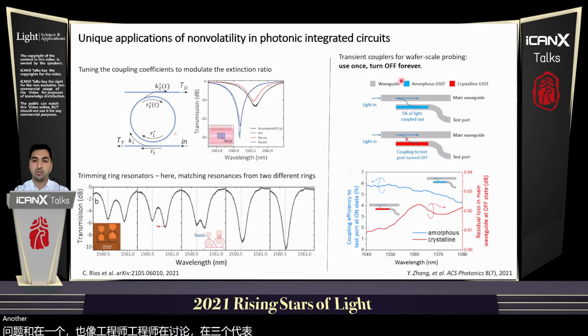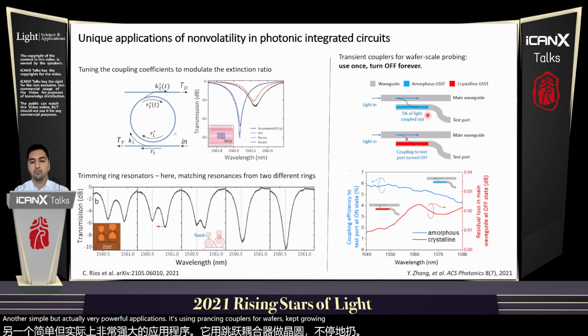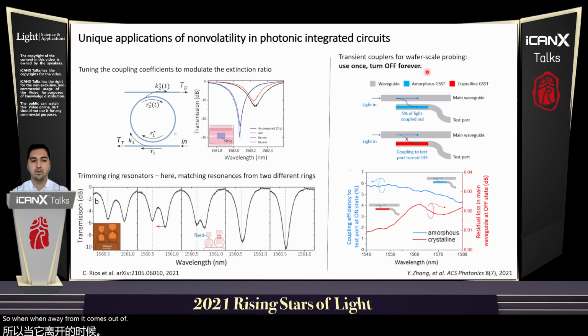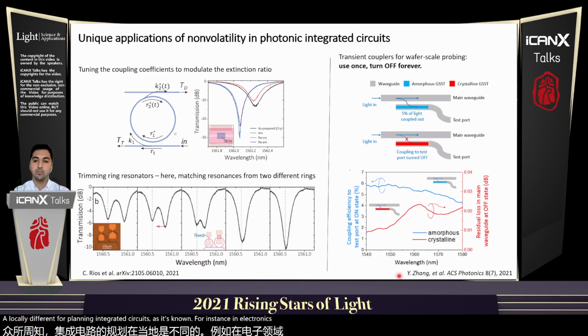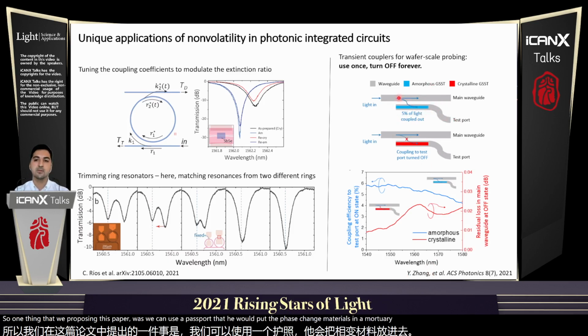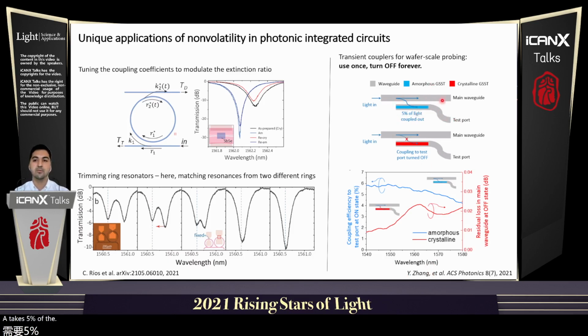Another simple but actually very powerful application is using transient couplers for wafer scale probing. When a wafer comes out of a foundry, it is really hard to probe different photonic integrated circuits locally, as it's done, for instance, in electronics. So one thing that we proposed in this paper was to use a test port that, if we put the phase change materials in amorphous, takes 5% of the light from the main waveguide. In this way, we can test if the different photonic circuits are working well.